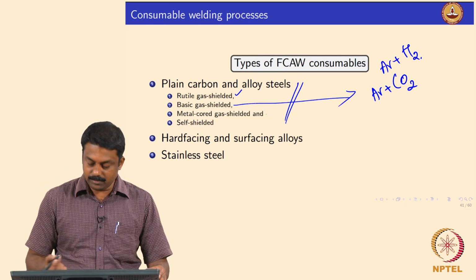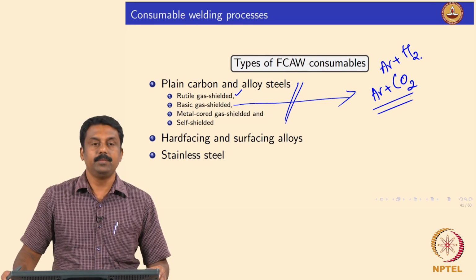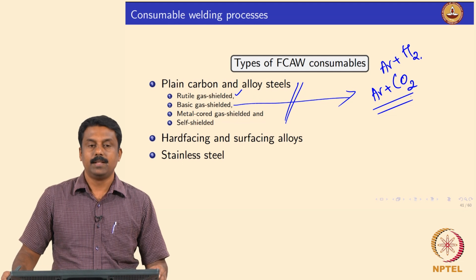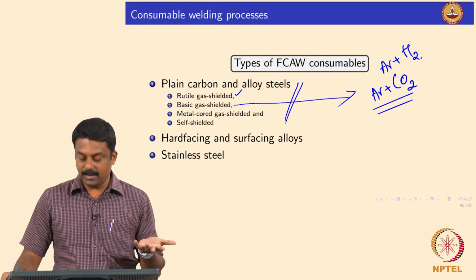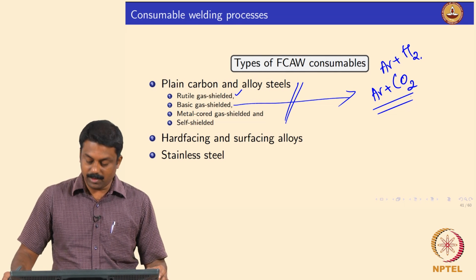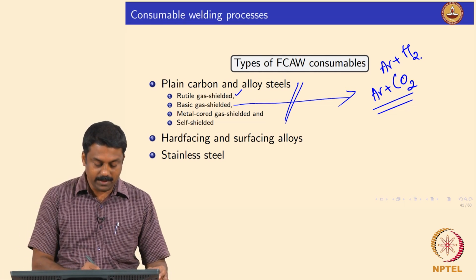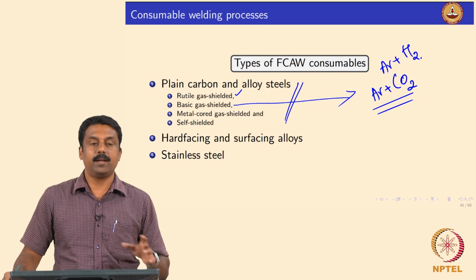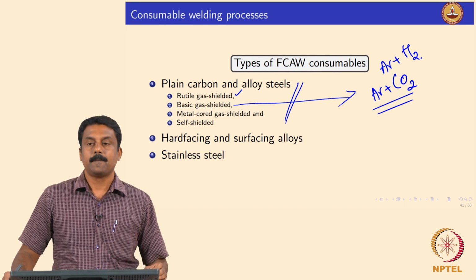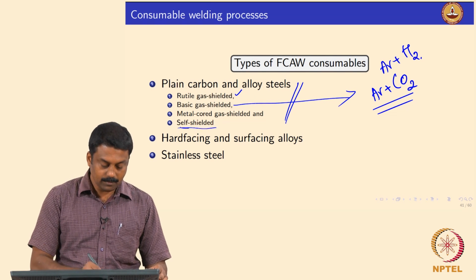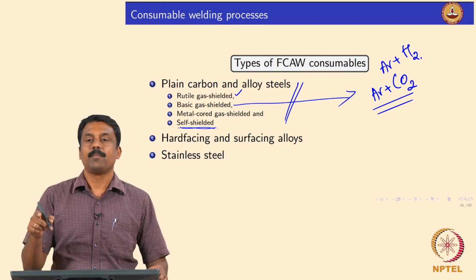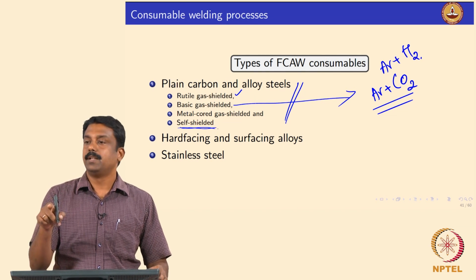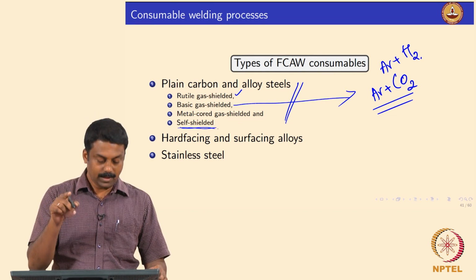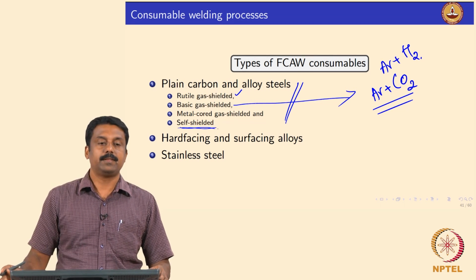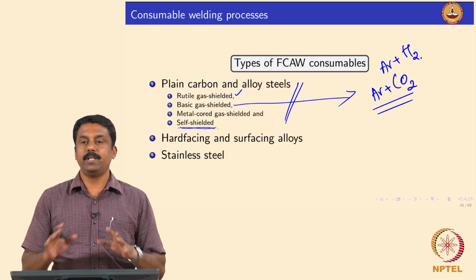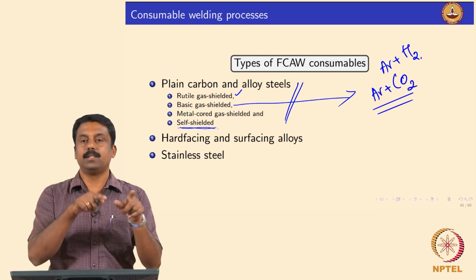And in FCAW, most of the cases argon plus CO2, right. It's because in most cases you will have calcium carbonate fluxes. So, you will have argon as external shielding and then CO2 generated from the burning of the flux. In self shielded electrodes, which I circulated, this is a self shielded electrode, you have the maximum amount of gas generated by the decomposition of the flux, right. So, we do not use any extra shielding for the electrode I just sent around,